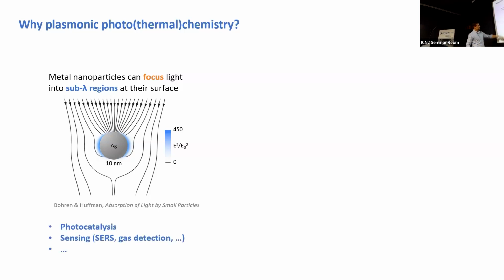Well, you can think that any photocatalytic reaction will start by excitation of an electronic system to a higher electronic level, for example, and it will always be modulated by the intensity of the electric field through the Fermi golden rule. So if we now have an intensity enhancement of orders of magnitude, then the rate of photocatalytic reaction can be enhanced dramatically, precisely at the surface where you also have catalytic properties because of the catalytic properties of metal nanoparticles.